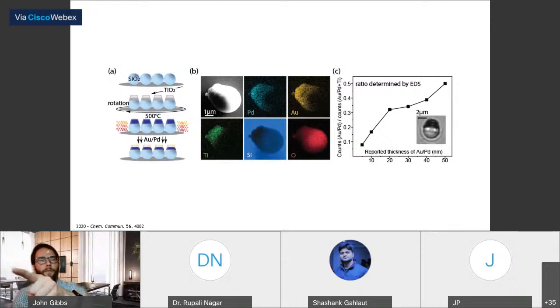If you look at the left side, figure A, it's a tail of TiO2. It's a little bit stubby, right? It's not a long tail like we had for the other ones. Then we put gold directly on top of those tails. This was done using glancing angle deposition. We tilted it to a large angle and spun the substrate rapidly during the deposition process, so you get these fat tails on the end. It's a different morphology than keeping the substrate at a fixed angle.